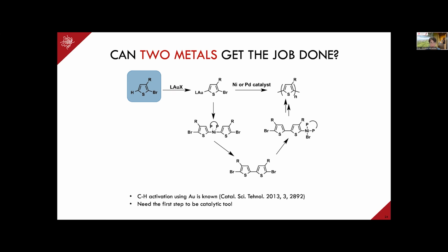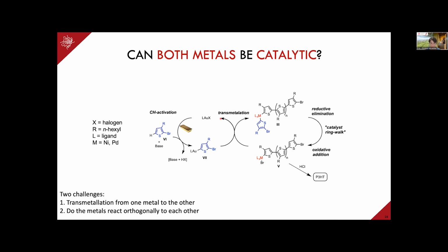So in order to redraw this, what we really need is the following. We have one catalytic cycle that's doing the CH activation, but then at this stage, it needs to hand over to the catalyst that does the polymerization, and you get the controlled polymerization going. In order to get this to work, there are multiple challenges, one of which is, can we get the transmetallation from one metal to the other to work at the right point? But also we needed to identify two catalysts that would not interfere with each other. And we were able to identify such a system. As a starting point, we used gold. And then for the catalyst to do the polymerization,